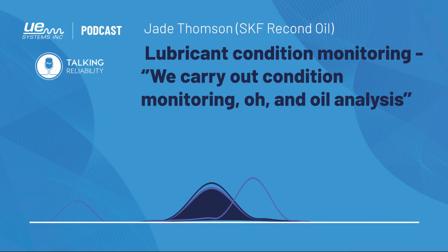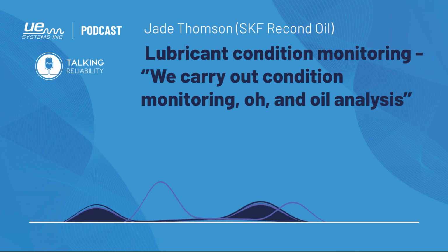I work for an OEM. OEMs put a lot of work into telling us what lubricants we should use in our assets, but it's theoretical. They cannot cater for every single application and process, and a lot of us will use assets in scenarios and processes where they're not usually used. So we do have to optimize that slightly, do some routine analysis, and then do some suitability testing and decide, actually, we should be using a 320 grade here rather than a 220 because we're running it at 80 degrees instead of 60. Hopefully this all makes sense so far.